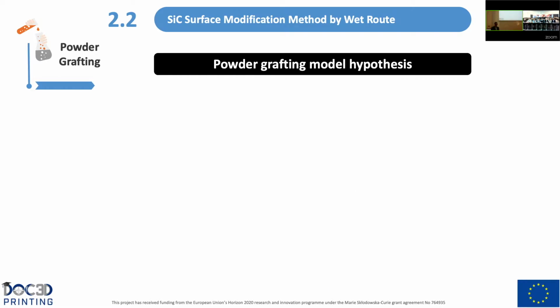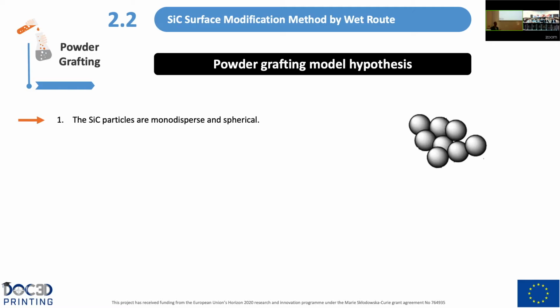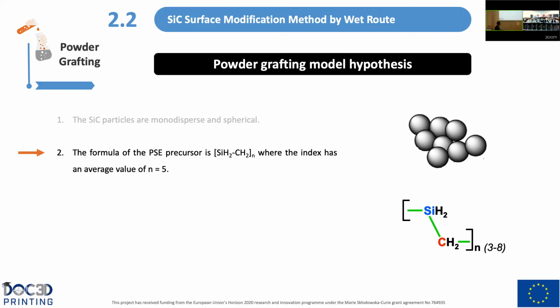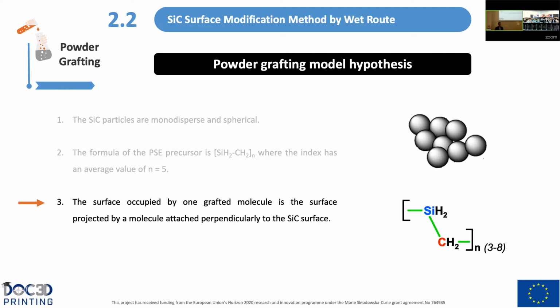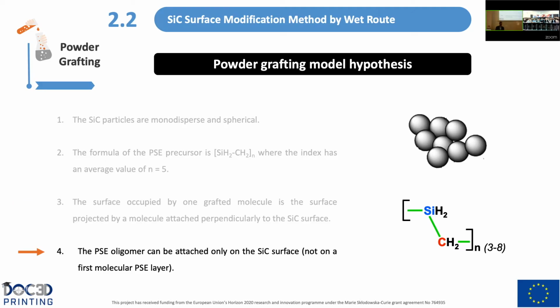So now, what we want to do is to know the mass of the polycarbosilane oligomer that we need to graft all the powder. So for that, we developed the following model hypothesis. Firstly, the silicon carbide particles are monodispersed and spherical. Then, the formula of the polycarbosilane has an index of 5. Next, the surface occupied by one grafted molecule is the surface projected by a molecule attached perpendicularly to the silicon carbide surface. And finally, the polycarbosilane polymer can only be attached on the silicon carbide surface and not on a free molecular polycarbosilane. And by developing this hypothesis, as you can see in an analysis that I have prepared, we can arrive at this expression to know the mass that we need to graft our silicon carbide powder.